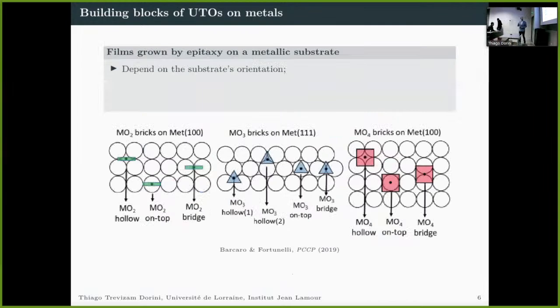And to complicate it even more, the type of tiling configuration also changes according to the epitaxial relationship with the metallic substrate. For example, you have a different set of oxide formations when the oxide is supported on a metal 111 than when you have it on a metal 100, as you can see in this image. So as you see, there is a huge number of possible configurations on an oxide, which depends on the oxide composition, its epitaxial relationship with the metal, and the temperature and pressure conditions.